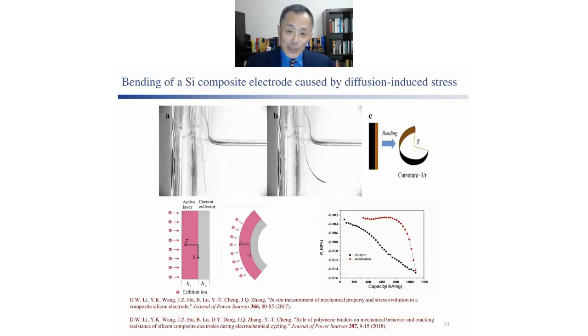And still, because of the volume expansion and contraction, large stresses can be generated in the silicon composite electrode, as shown here by these images of a bilayer cantilever consisting of an electrode layer on top of a 20 micrometer copper foil. The stress is so significant that the curvature change can be observed visibly with a simple video camera. By analyzing the curvature and by measuring the thickness of the electrode, one can obtain both the elastic modulus and the stress in the electrode. More details can be found in these publications.